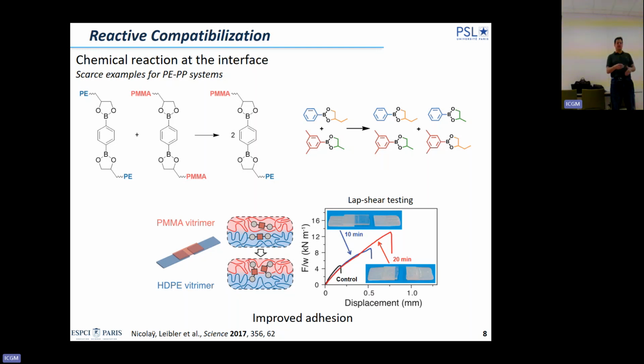We put them into contact at 190 degrees Celsius without any kind of treatment of the surface, nothing. And then if you wait long enough, in our case, 10 or 20 minutes, this was clearly not optimized, and you do the lap shear test, the adhesion at the interface between PE and PMMA is so strong that we always break in the bulk of PMMA. So this is an indication of the creation of a strong bond.